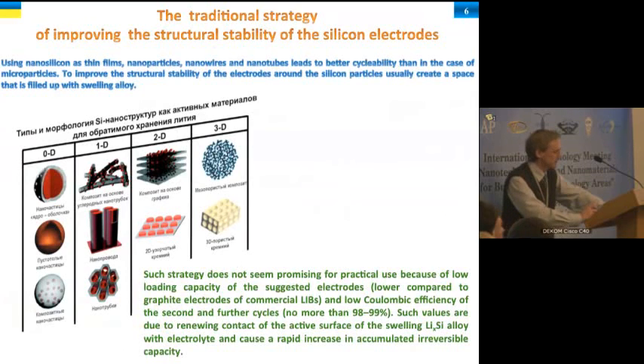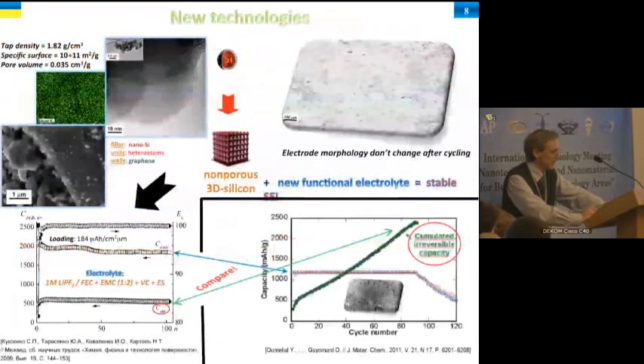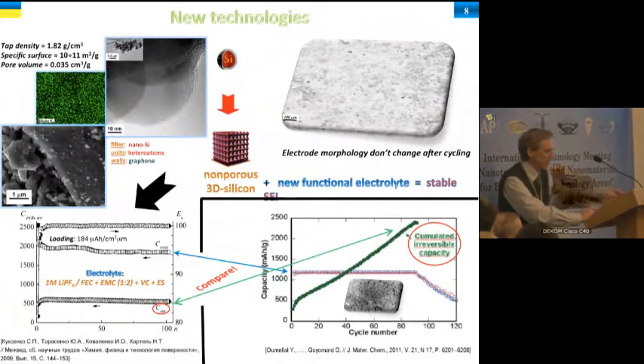With the aim to reach acceptable values of accumulated irreversible capacity at high capacity loading, we propose a new nanocomposite configuration wherein the silicon nanoparticles are deposited on a conformal coating from graphene layers interconnected together through thin heteroatoms, which gives them mechanical strength. Such coating is highly conducting and electrochemically active with respect to incorporation and release of large amounts of lithium. With this new nanomaterial, it is possible to control the strain of the lithium silicon alloy, thus preventing its contact with electrolyte and to fabricate high-density silicon-containing electrodes.